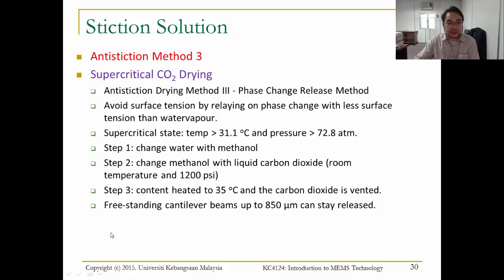Okay, the step-by-step process involves, first of all, changing water with methanol. So we substitute water with methanol, and then change methanol with liquid carbon dioxide from room temperature and at 1200 PSI. And then step number three, we heat the content to 35 degrees Celsius and the carbon dioxide is vented. Freestanding cantilever beams up to 850 micrometers can stay released without any stiction by using this process.